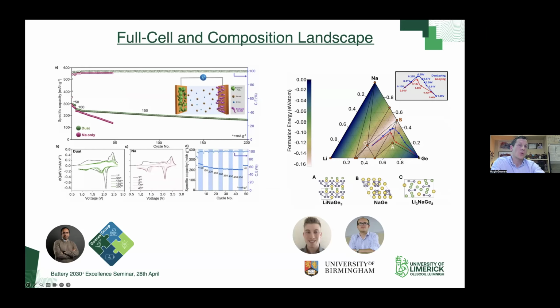So essentially what we're showing is that this initially passes through a chemical environment that is roughly LiNaGe2. Okay, so roughly equimolar there in terms of Li and Na. Then it moves down to this lithium-rich domain that you see here, where the formation energy is low, and then passes back up through nearly to NaGe. Okay, so again, this is the kind of energetically favorable path that this takes through that ternary phase landscape that you see up here. Okay, so this was a nice finding that matched what we had seen from the ICP